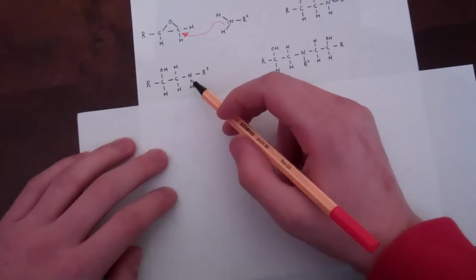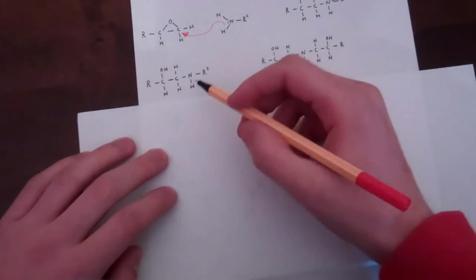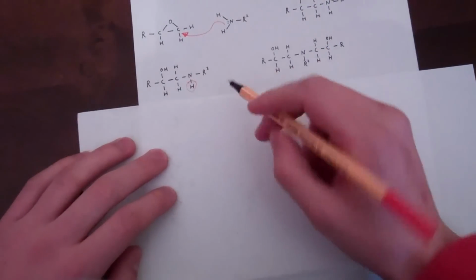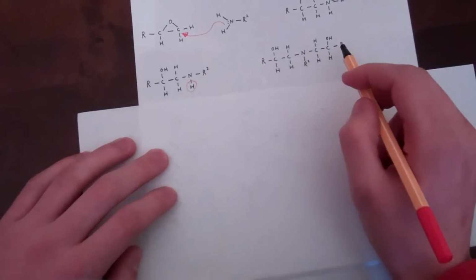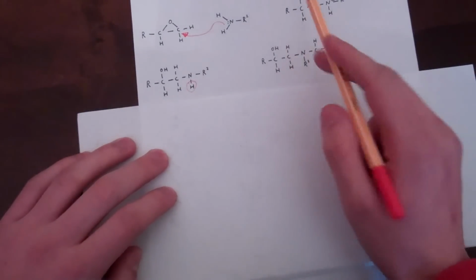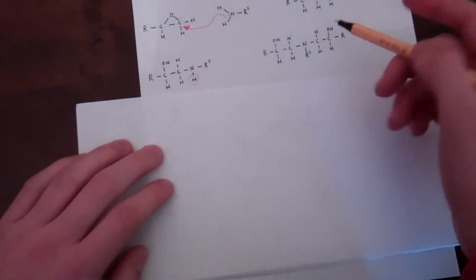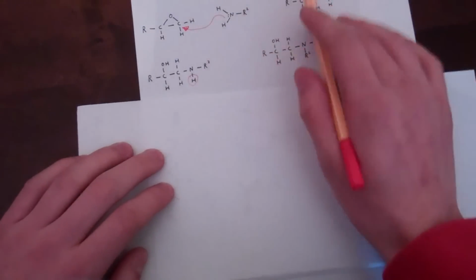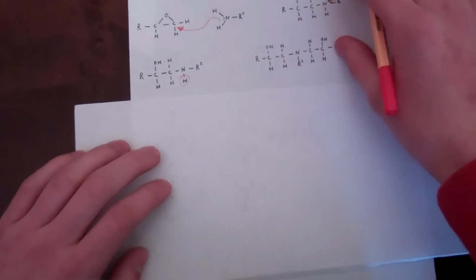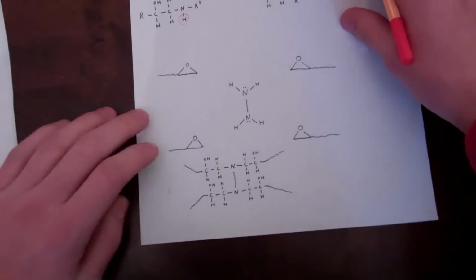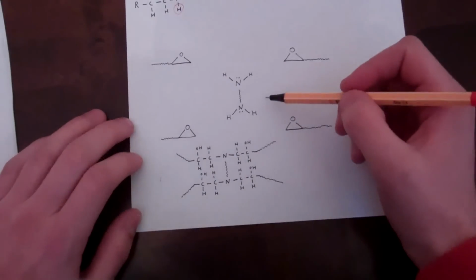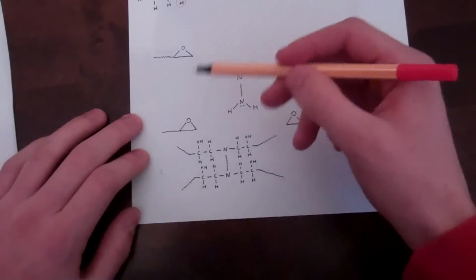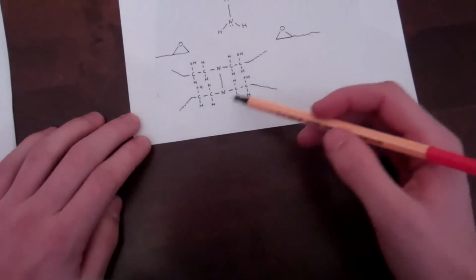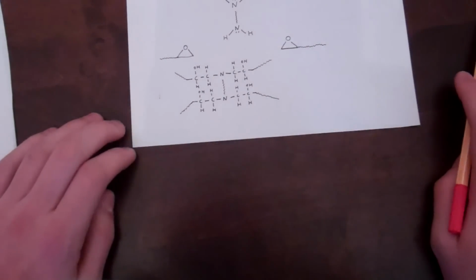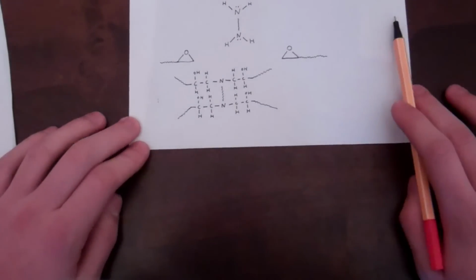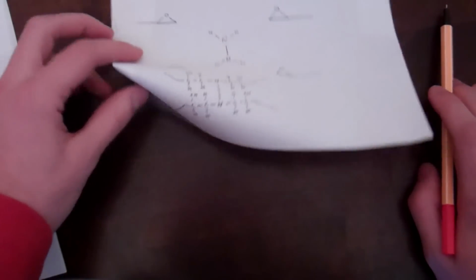This forms this. By undergoing the same reaction on the other hydrogen here, attached to the nitrogen, we can see that we attach compound groups to either side of one end of the activator. And because R2 here includes the other amine group at the other end of the molecule, we can see from down here that one activator can be attacked by 4 different compounds, which forms this complex structure down here. All this leads to a massively cross-linked polymer, which forms one giant lump of epoxy resin in the whole.